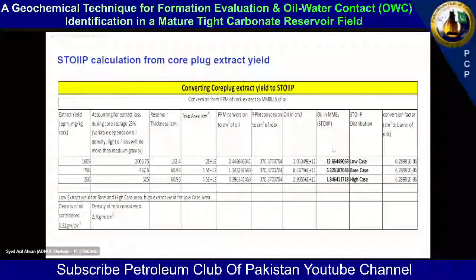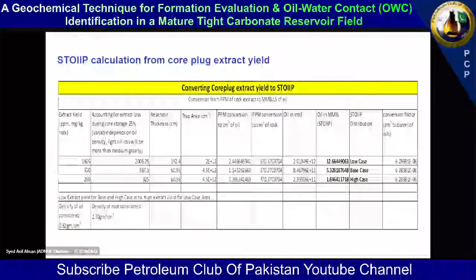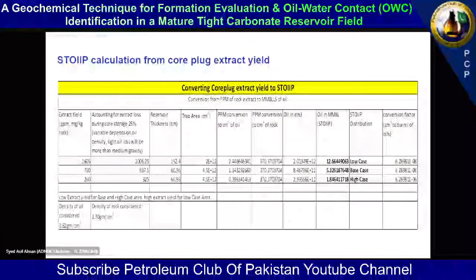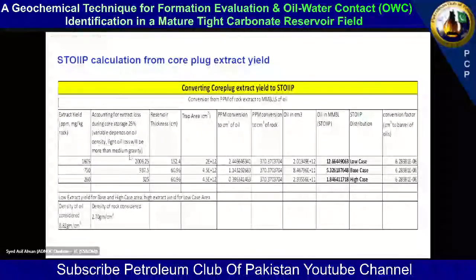Of course, there are some losses. This is the extract yield that I've actually measured on samples. This is the average of a few samples in the low case. This is the average of a few samples in the base case, and this is the average of a few samples coming from below the base case and above the high case. And of course, I've assumed a 25% loss, although the loss is much more than that.